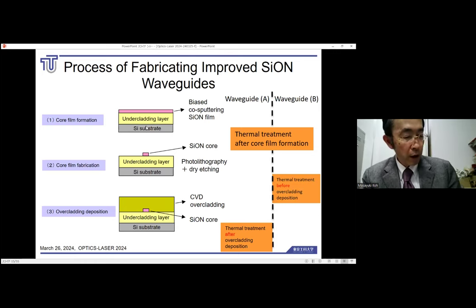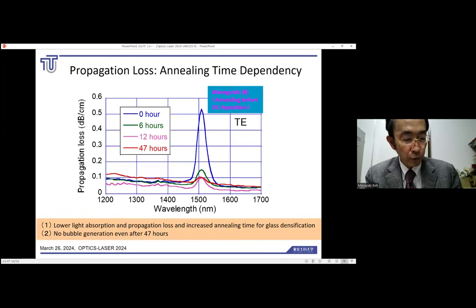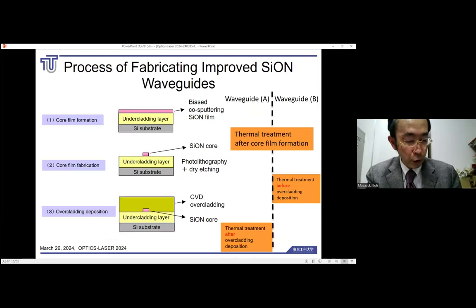deposited by co-sputtering. The subsequent heat treatment process is the same for both waveguide A and waveguide B. Next, the core is processed through photolithography and dry etching processes. After this, waveguide A is left as it is, and only waveguide B is heat treated. Finally, overcladding is deposited using the CVD method to embed the core. After this, only waveguide A is heat treated, while waveguide B is left untreated. The two waveguides are heat treated differently before and after the overcladding deposition to investigate the differences in their optical properties.